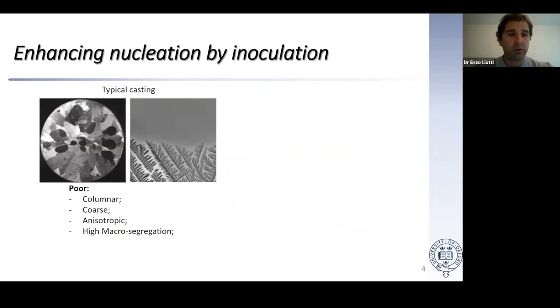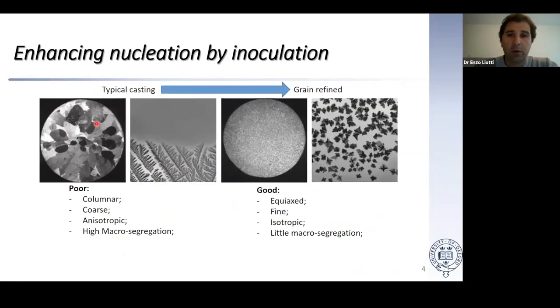In particular, if we look at casting an aluminum alloy, if you try to cast something, probably what you obtain is exactly what you see in the image, a columnar coarse microstructure, right? That's the typical, let's call it natural microstructure you obtain when you cast something. But what you would like to obtain is a grain refined microstructure, so where equiaxed fine isotropic grains form instead of this columnar dendrite. The equiaxed structure retains many advantages compared to the columnar one: mechanical properties are better, you get fewer defects and so on, less macrosegregation.